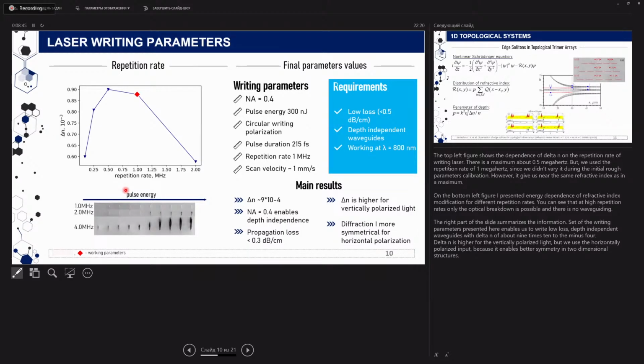On the bottom left figure, I presented energy dependence of refractive index modification for different repetition rates. You can see that for the higher repetition rates only optical breakdown is possible, and there is no waveguiding. The right part of the slide summarizes the information. A set of writing parameters presented here enables us to write low loss, depth-independent waveguides with delta n of about 9 times 10 to the minus 4. Delta n is higher for the vertically polarized light, but we use horizontally polarized input because it enables better symmetry in two-dimensional structures.